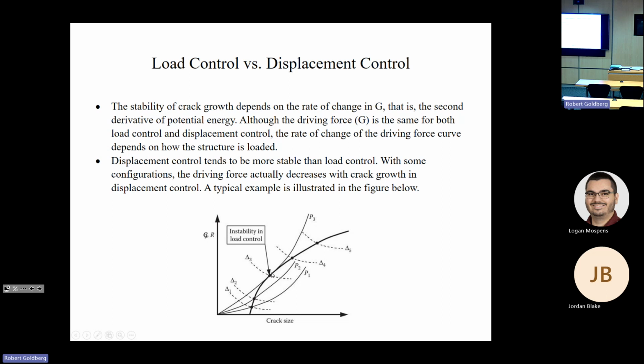So as the crack goes beyond here, the slope of this P3 curve is greater than our R curve, so we'll have unstable crack growth. However, if this was displacement controlled, where we control the displacement, the structure is stable because even as the crack size grows, the slope of our resistance curve is greater than the slope of our strain energy release rate curve. So we have stable crack growth, and for further crack growth to occur, we actually have to increase our displacement. So that's what'll allow our driving force to be at the point where things will actually grow.